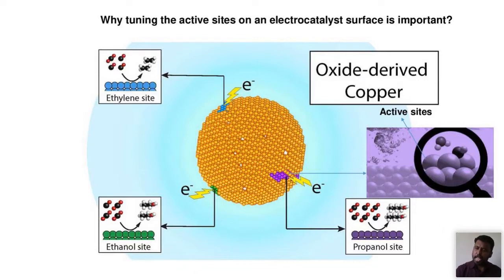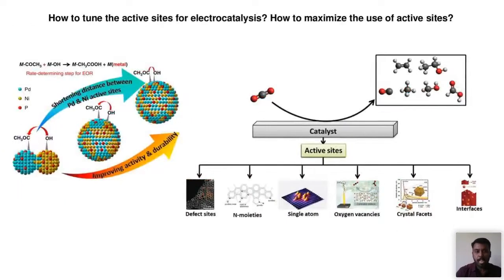For example, if you are interested in producing ethanol, or propanol, then you can create more ethanol sites, and also you can create more propanol sites on an oxide derived copper. Instead of having everything, it will affect your yield. For instance, if you have 20% ethylene site, 50% propanol site and 30% ethanol site, you will not have high activity. In that case, you can have more ethanol or propanol sites based on your requirement. So active site engineering is very important.